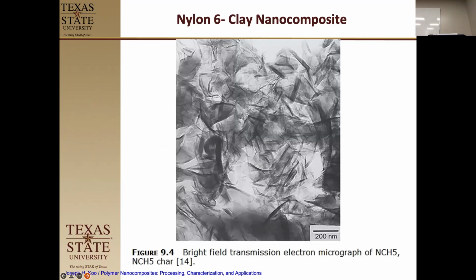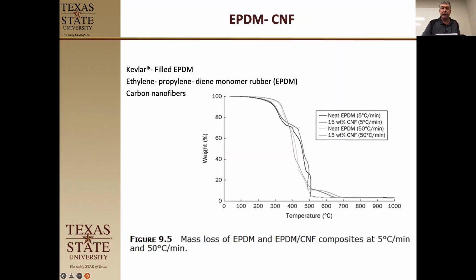I believe this is the 5% right here. So they actually had a pretty good job of exfoliating. You can see they're all kind of lined up behind. And they processed it, I believe, through a twin screw extruder. They did a master batch and then we did a batch to get the 5%. So you wouldn't think nylon would be one of the best ones for that, but they did do okay.